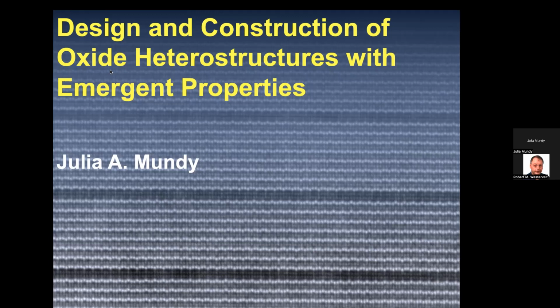And it turns out that the magnitude of this distortion directly impacts the magnetism, the magnetic properties in that adjacent layer. And so in this way, we're not only able to control where we put atoms down, but we're further able to control with picoscale resolution the structure of the materials, which can have profound impacts on the properties. So I think this is really cool. I think this is some of the finest control of materials that you can have by any technique.